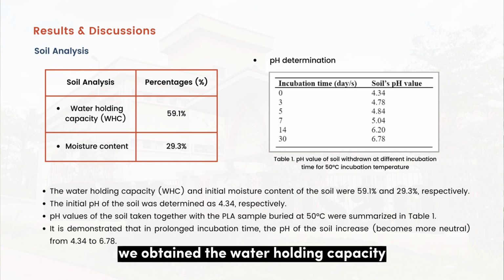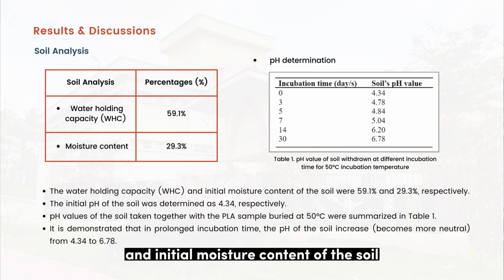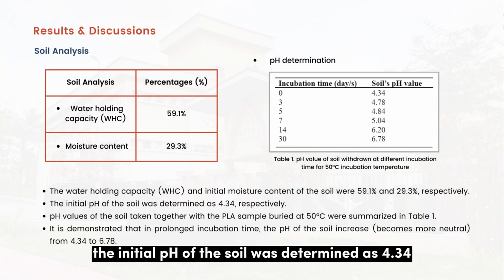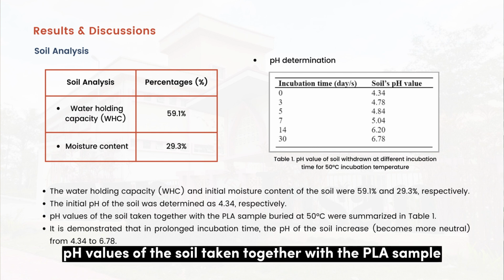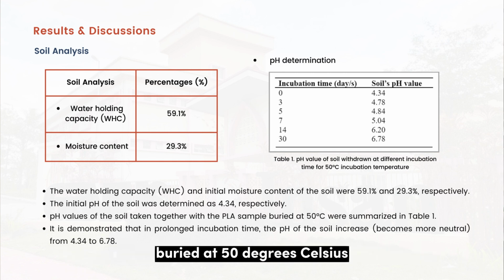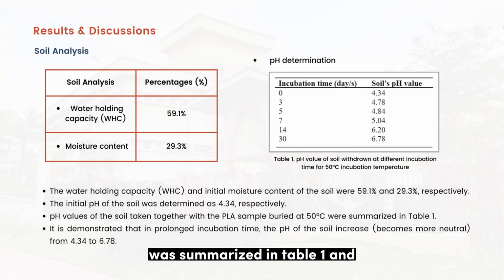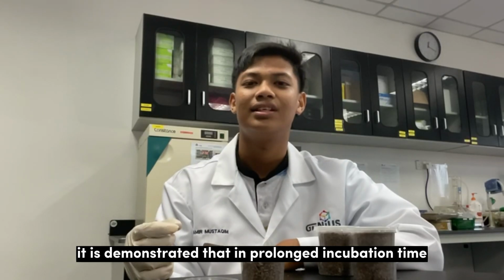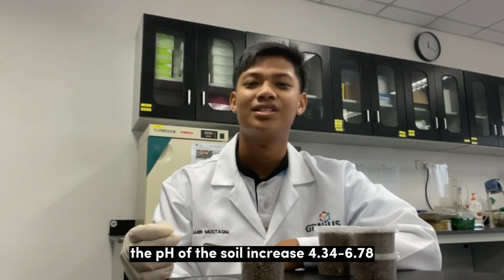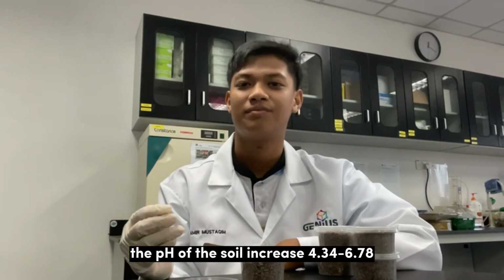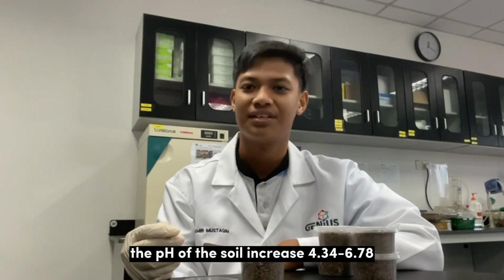For soil analysis, we obtained that the water holding capacity and initial moisture content of the soil were 59.1% and 29.3% respectively. The initial pH of the soil was determined as 4.34. pH values of the soil taken together with the PLA sample buried at 50 degrees Celsius were summarized in Table 1, and it is demonstrated that with prolonged incubation time, the pH of the soil increased from 4.34 to 6.78.